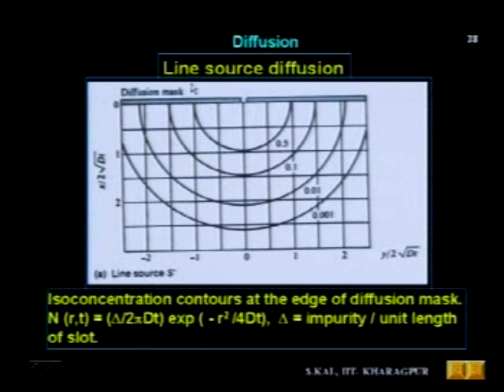Now this is the profile of a line source diffusion. A line source is here, the diffusion mask is here and here, and this is the line, and that is a cross section. That's why it is a small window you can see. If you see the top layer, then it is basically a line, and in this line source, these are iso concentration contours. The 0.5 is n by n surface.